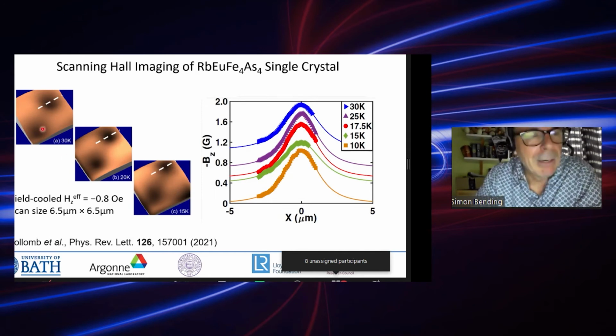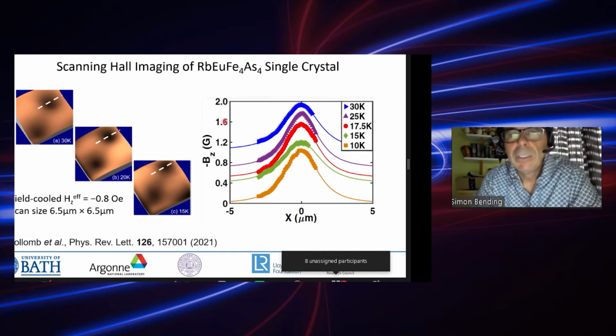But that's much clearer to see if you actually take a line scan across the middle of a vortex in each case. This is what I've plotted in this panel here. This is the field profile as a function of the spatial coordinate x. And you can see that when we start at 30 Kelvin and gradually cool down, initially the vortices actually narrow a little bit down to about 17.5 Kelvin. But then as we approach the magnetic ordering temperature, we see a pronounced broadening again of the vortex. And then as we go even lower still, it narrows again below that.